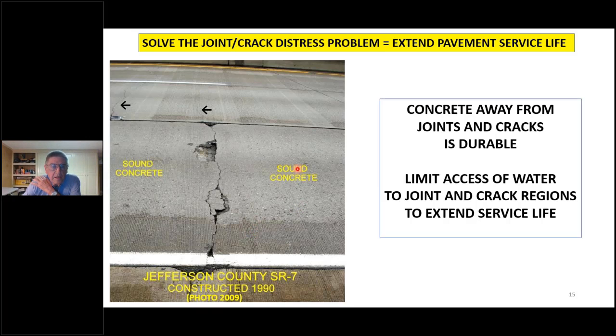We know how to make sound, durable concrete today. 19 of the 20 pavements from the study that I was involved in were just good old ODOT Class C concrete. Water-cement ratios were like 0.43 to 0.48. They were air entrained. Half of them contained fly ash, so they had low permeability. We can make concrete, and when you rehabilitate or remove pavements, the stuff on either side of the joints and cracks comes out as big, large chunks that are still in pretty good shape. So we know we can make good concrete. So we can get a handle on this situation here.